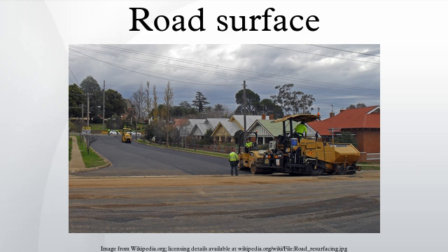In the 1960s, rubberized asphalt was used for the first time, mixing crumb rubber from used tires with asphalt. While a potential use for tires that would otherwise fill landfills and present a fire hazard, rubberized asphalt has shown greater incidence of wear in freeze-thaw cycles in temperate zones due to non-homogeneous expansion and contraction with non-rubber components. Also, application of rubberized asphalt is more temperature sensitive, and in many locations can only be applied at certain times of the year.